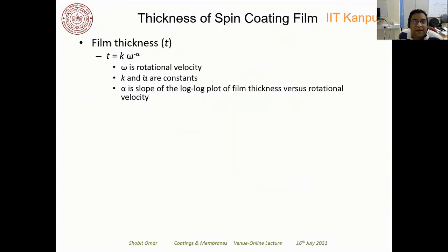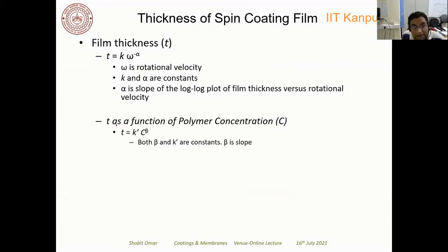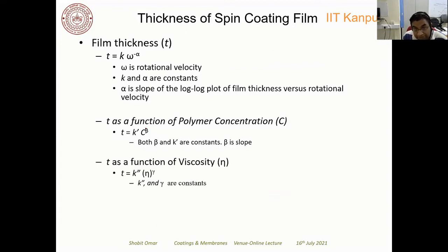So film thickness depends upon the rotational velocity, because rotational velocity will dictate what is the centrifugal force that you will apply. So higher is the velocity, smaller is the thickness, right? So this is the relationship that we have, that K and alpha are the two constants, right? And then thickness also depends upon the polymer concentration. If you have a higher concentration, then you will see that the polymer is more viscous. Then the thickness is basically dependent directly on the polymer concentration.